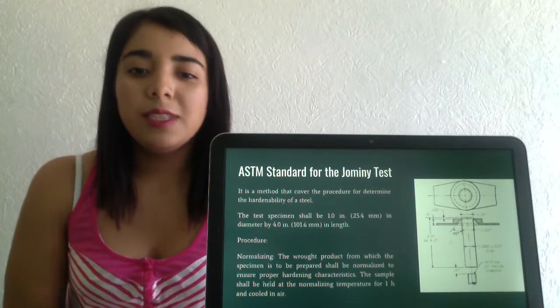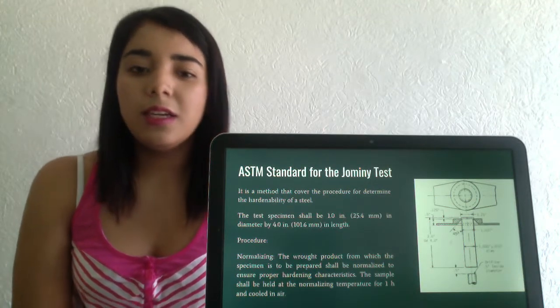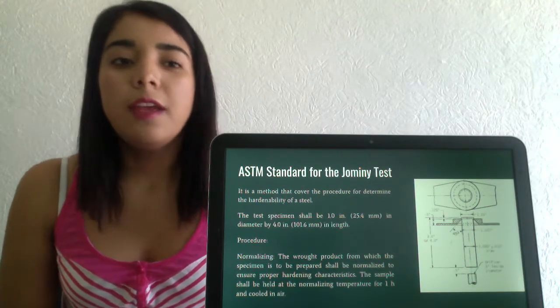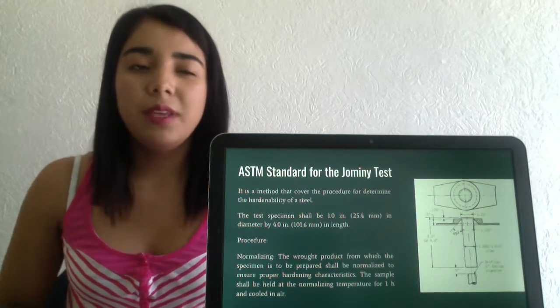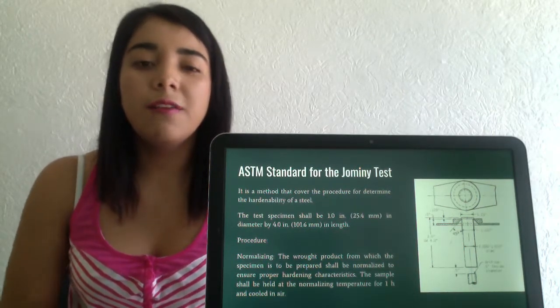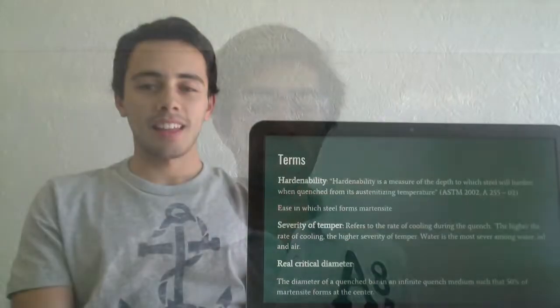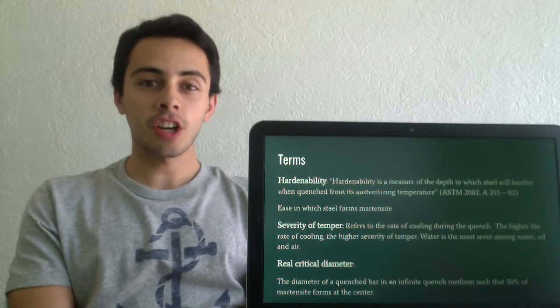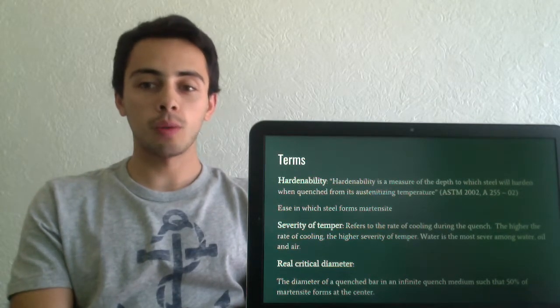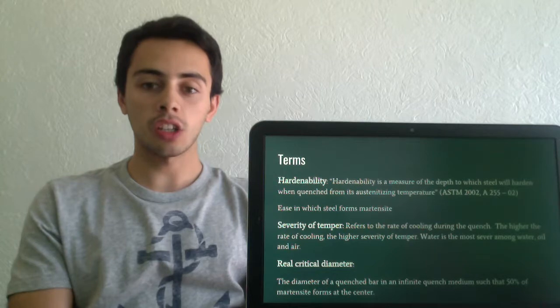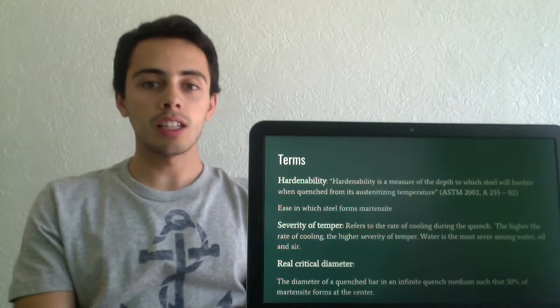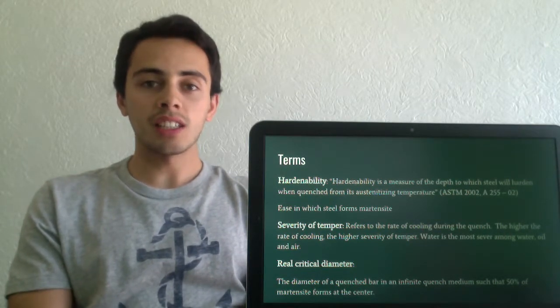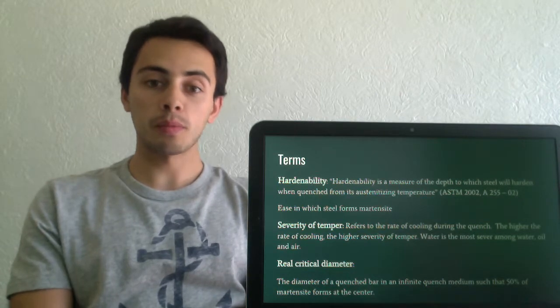The ASTM standard for the Jominy test is a method that covers the procedure for determining the hardenability of a steel. It covers what we already said in the experimental procedure. ASTM defines hardenability as a measure of the depth to which steel will harden when quenched from its austenitizing temperature. Therefore, it is basically the ease with which a steel forms martensite.